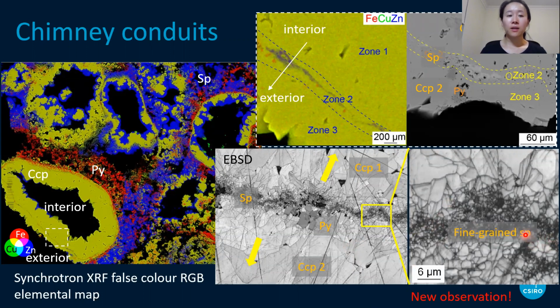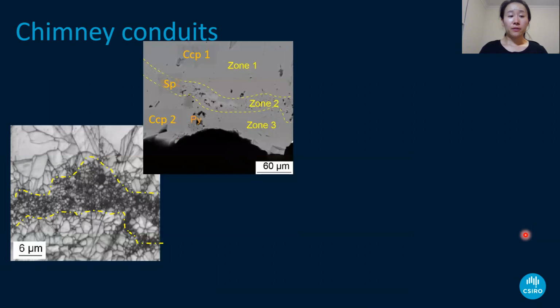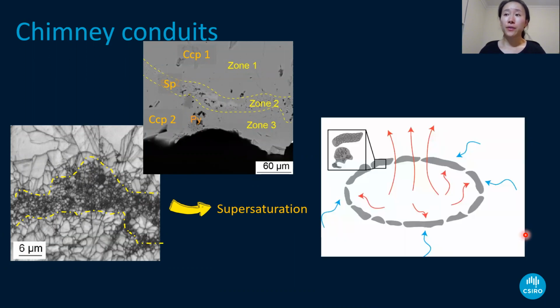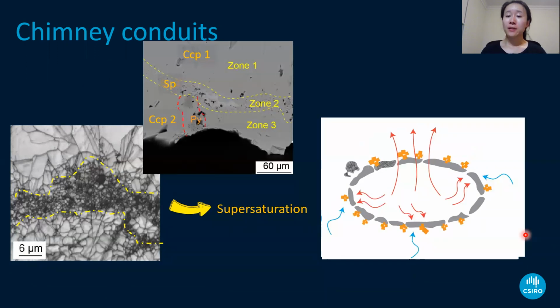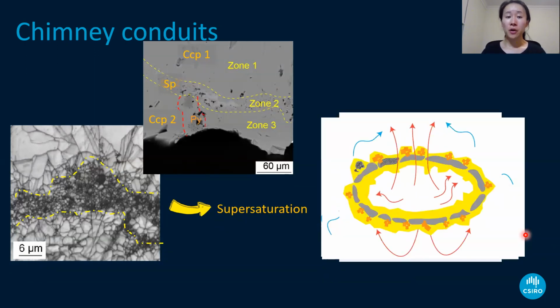What does it mean? The clusters of fine-grained particles usually indicate supersaturated conditions in the venting fluid. So this suggests that this layer is likely to be an initial layer resulting from the quick mixing between the hot venting fluid and the cold seawater. And then during the further mixing, the pyrite and the chalcopyrite continue to overgrow from this layer.